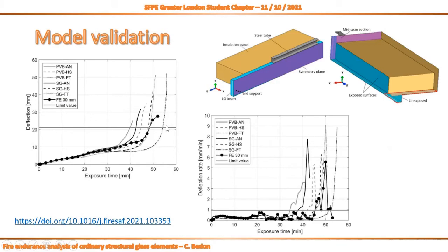For sure, you can see some scatter at the final stage of bending response, but you can also see that for most of the fire exposure, and we are talking at least about 40 minutes of fire exposure, the match was very good in terms of deflection in time. And so this means that the modification of bending stiffness for this composite section was properly taken into account with the basic input parameters for material.